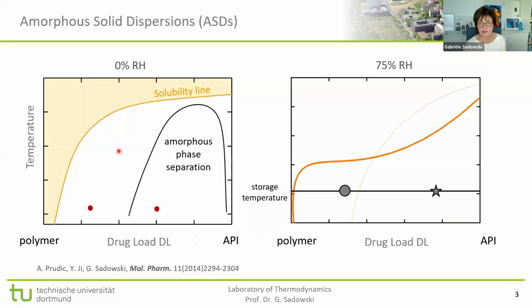So where we have a certain RH, for example, 60% or 75% if it's quite humid. And that means that now we have three components in the system. We have the polymer, we have the API, and we have water. And the water will change the solubility line. So this was what it might look like for a dry system. And for the dry system, this point would have been crystallized, whereas this point for the dry system was left of the solubility line, so was safe, so to say.